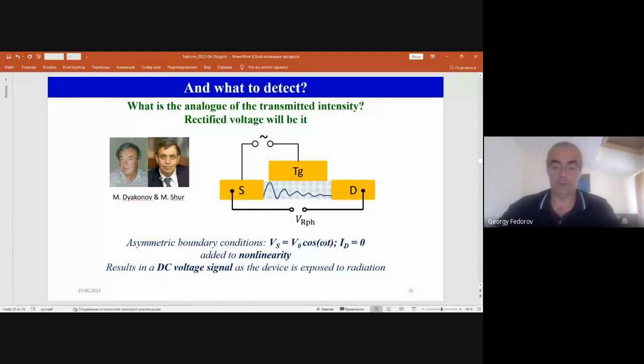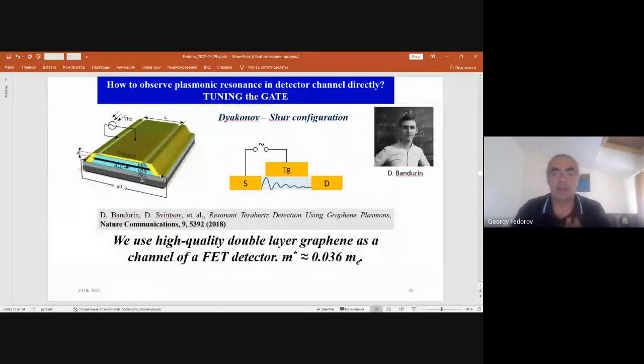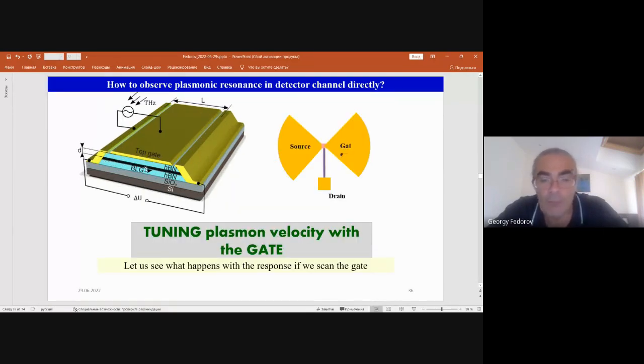this, oh, sorry, I'm going the other way around. So this was suggested by our colleague Denis Bandurin back in 2017 or so. The device is based on bilayer graphene, which is better in certain respects than single-layer graphene because its dispersion relation is not massless. So you have a finite effective mass that doesn't depend on gate voltage in a wide range. So you have better tunability. And encapsulated graphene is known to have very high mobility, so it can be used for this purpose.